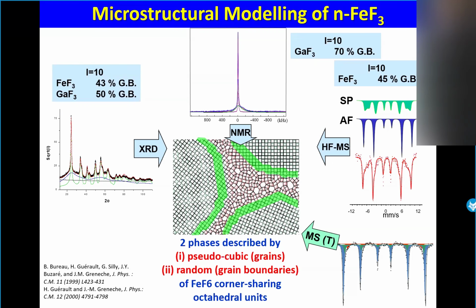So finally, by considering this layer, it was possible to obtain the same quantity for grain boundaries, 43%, 45%. And of course, we performed Mössbauer at different temperatures. Here we can see that there are 2 or 3 components, one attributed to the grain, one attributed to the amorphous, which can be assimilated to grain boundary, and in addition, a third one in between that corresponds to the green one.